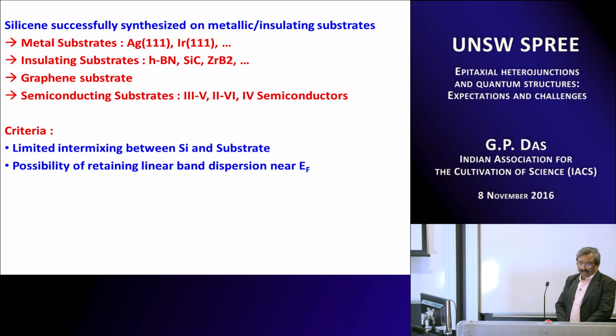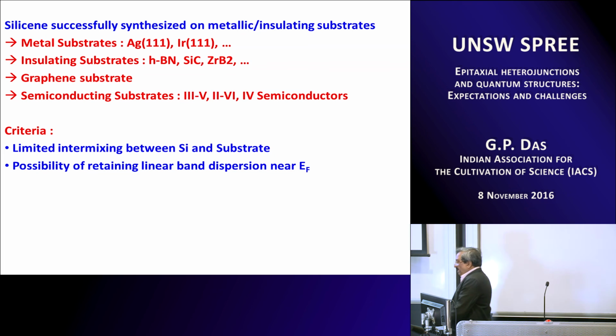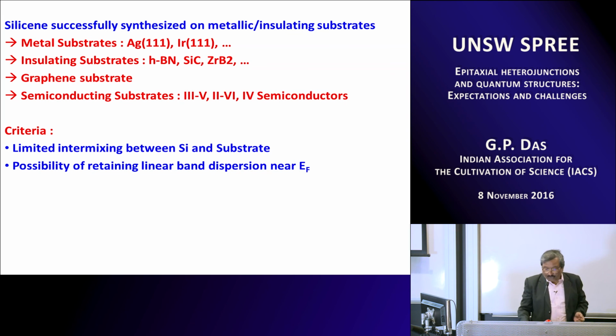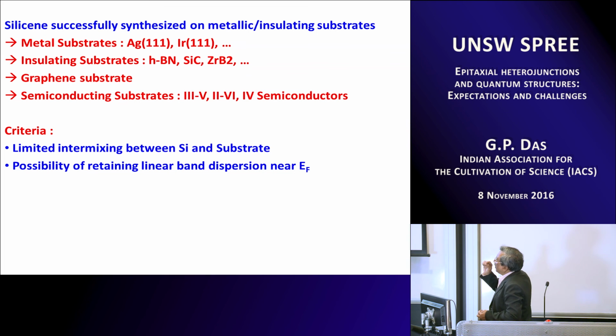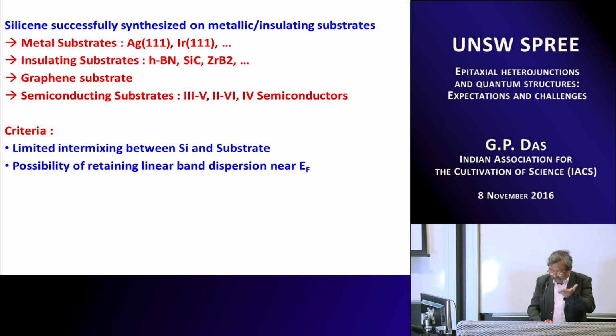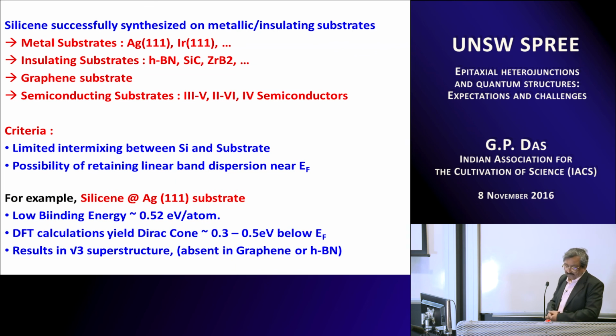Now the criterion is that there should be limited intermixing between the silicon and the substrate. What I mean is the following: if there is a very strong bond above a certain value, then the linear band dispersion characteristic will be completely lost. So what is needed is to have a nominal bonding between the silicene and the substrate on which you are depositing the silicene.